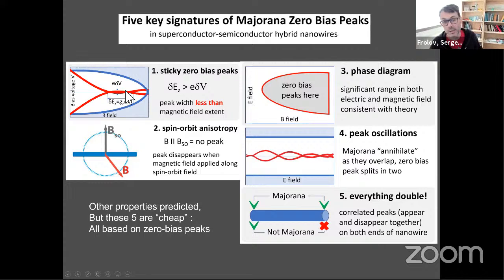So the first signature is already talked about, this zero bias peak that kind of comes to 0 and then doesn't leave, right? So that's fine. You want to start with that. Then what else can you look at? Well, in our system, we can explore the spin orbit anisotropy, which is a property where this spin orbit effect is parameterized by an effective magnetic field that points in a certain direction. And that means that the external field that we apply has to be perpendicular to the spin orbit field to see something, to open this gap due to spin orbit. So if we align the 2 fields, the zero bias peak should go away. This can be checked. We have checked it, and we found on a number of occasions that this is indeed the case.